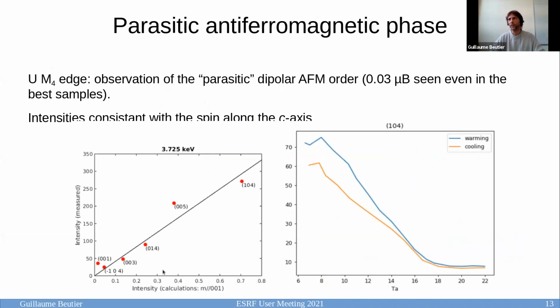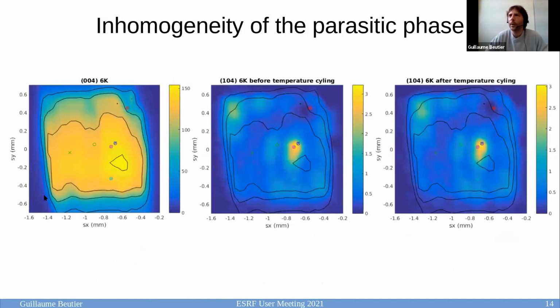At the uranium M4 edge, we saw the parasitic antiferromagnetic order, which is seen in all the samples, even though it's small. And we could confirm that the spin is aligned with the c-axis. It matches very well with the intensity of the diffraction peaks we had. Also, the temperature dependence is in agreement with what can be expected from that. So now what was surprising for us is that we did a map of the sample. We did both the charge peak, the 004, which is almost homogeneous, I would say. And we looked at the magnetic peak, the 104, which is on the contrary very inhomogeneous. So that was quite surprising. And we did cycle the temperature above the hidden order transition. And when we come back to the hidden order phase, we find the same magnetic map again, which seems that this parasitic phase seems to be pinned somehow.